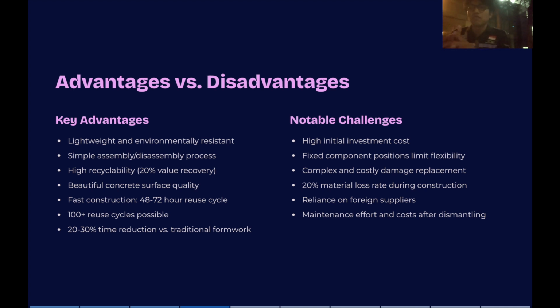And then the advantages versus the disadvantages. Why use aluminum over traditional timber or steel? The advantages are clear. It is 100% recyclable, provides a beautiful concrete finish, and most importantly, it enables a 48 to 72 hour reuse cycle. This leads to a 20% to 30% reduction in total construction time. However, we must acknowledge the challenges. There is a high initial investment and a reliance on foreign suppliers. Because the component positions are fixed, the system has less flexibility for design changes once on site. Therefore, precision in the planning phase is mandatory.